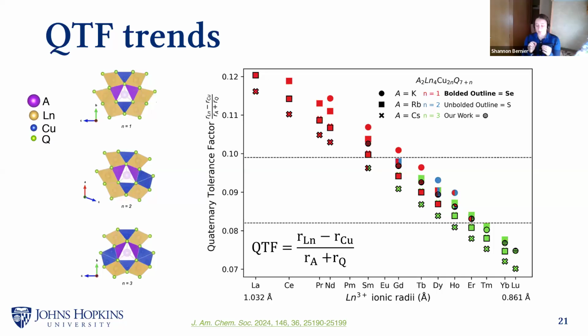The reason that the QTF is able to predict this transition is because tolerance factors and the QTF specifically are talking about the bonding arrangements. They're talking about how the atoms with a fixed radius are packing specifically tightly together. And the transition going from high lanthanide radius here onwards is a smooth sort of transition where we have the addition of a new copper selenide or copper sulfide group around the bonding environment of the A site cation as we move from the n=1 to the n=2, and then finally an additional copper selenide or sulfide group as we move into the n=3.